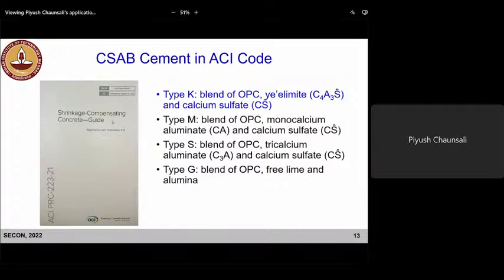So there are already standards. I am showing you the recent standard, the shrinkage compensating concrete guide by the American Concrete Institute, ACI 223, which goes through the design. Okay, how do we use these cements to develop shrinkage compensating concrete? So there is already this ACI standard, and in this standard they talk about different expansive cements. So one of them is type K, which is nothing but a blend of Portland cement and yeelimite, right, which is the calcium sulfoaluminate phase, and calcium sulfate. So when we mix Portland cement with yeelimite and calcium sulfate, you get this type K cement.